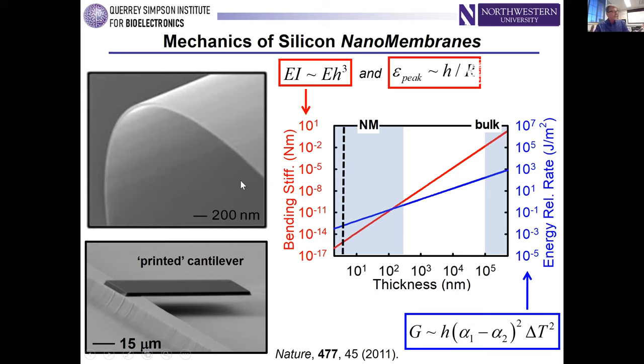So if you think about that kind of heterogeneous integration, now you're talking about how do I manage the bonding interface between a piece of silicon and a piece of silicone rubber, for example. That's a very difficult interface to manage from an adhesion standpoint. But here, thickness scaling comes to your rescue again, because the energy release rate parameter G scales down linearly with thickness. So as I make the silicon thinner and thinner, the interface stresses that would otherwise tend to drive delamination from an underlying plastic or rubber substrate are suppressed by a very significant amount as you go from a wafer scale object of silicon to something like a silicon nanomembrane.